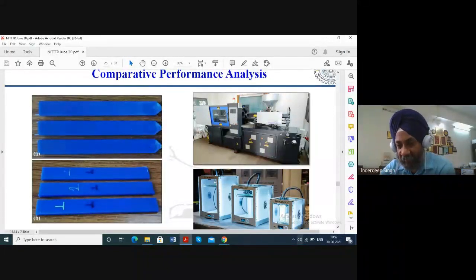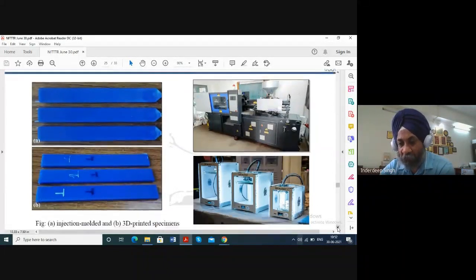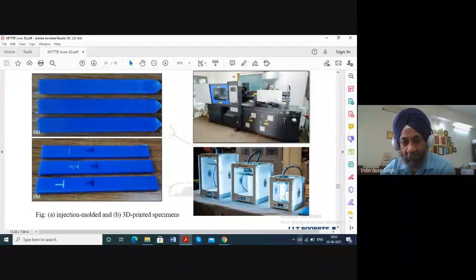And this is the Ultimaker setup that we used for 3D printing of our parts, FDM. So these are the injection molded and 3D printed specimens. These are 3D printed, and the material that we investigate is an environment friendly material, that is PLA. These are the samples which were fabricated, and then their mechanical properties were compared.